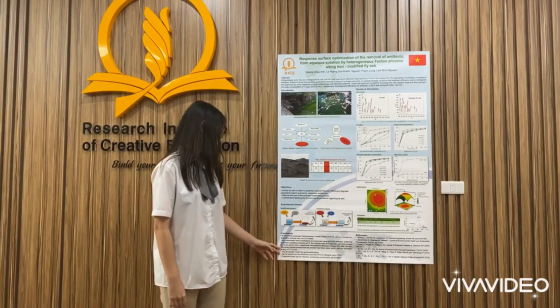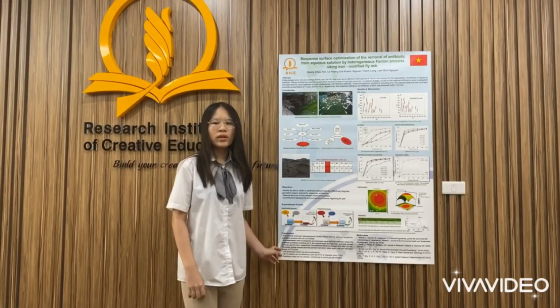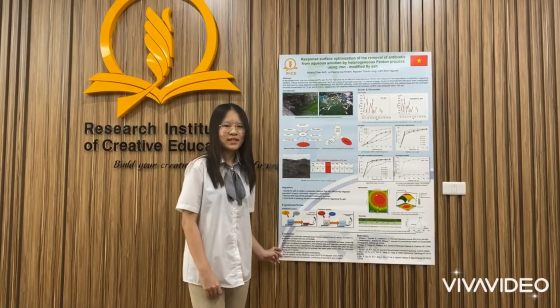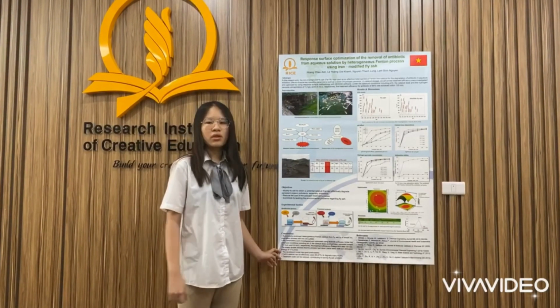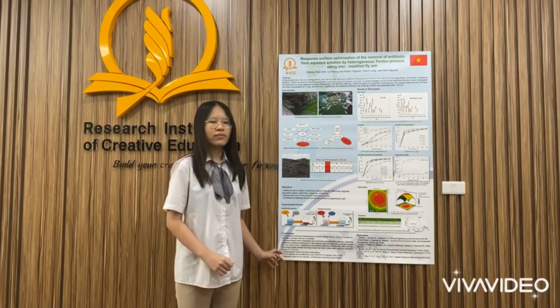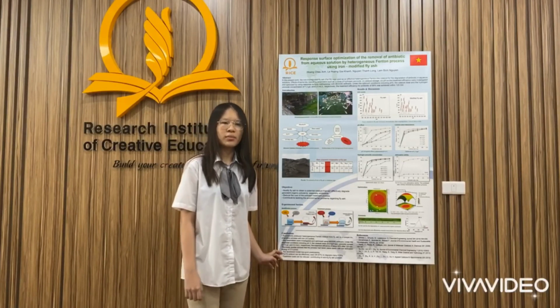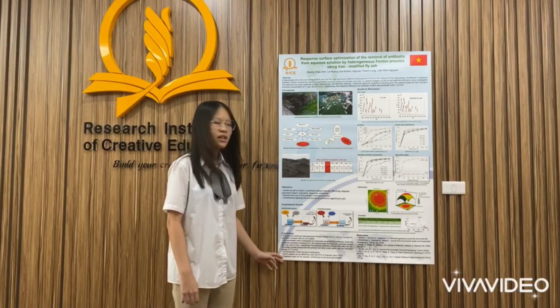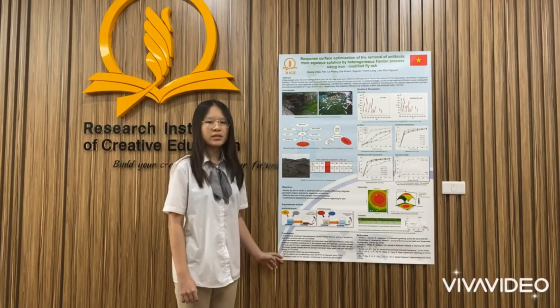The kinetic study showed that the process took place easily, with a low activation energy of 17 kilojoules per mole. The advanced model has good predictability. Iron modified fly ash can be effectively used to degrade many persistent organic pollutants. And lastly, treatment costs can be reduced, contributing to solving fly ash problems.